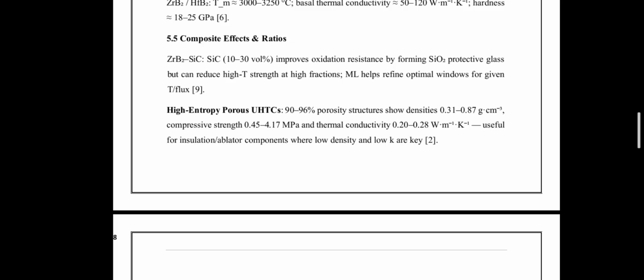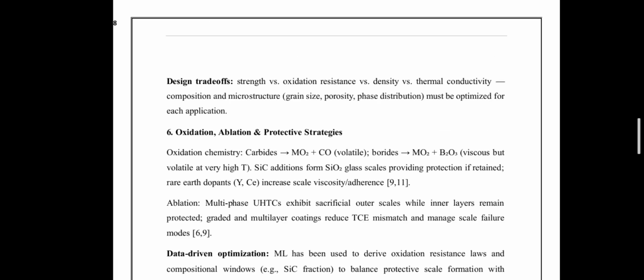High entropy porous ultra high temperature ceramics exhibit a very low density and thermal conductivity, making them suitable for insulation or ablative roles rather than load bearing components. Ultra high temperature ceramic design is a multi objective optimization problem where we have to consider strength versus toughness, oxidation resistance, thermal conductivity, density, and thermal protection. These trade offs are resolved through composition, microstructure, and processing control, increasingly guided by data driven and ML approaches.